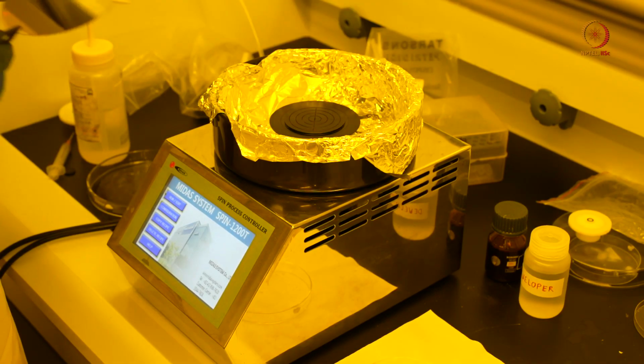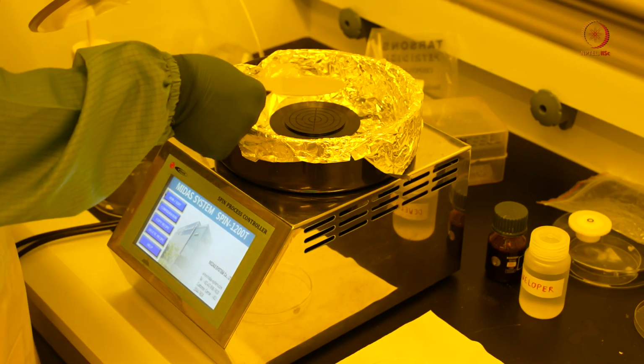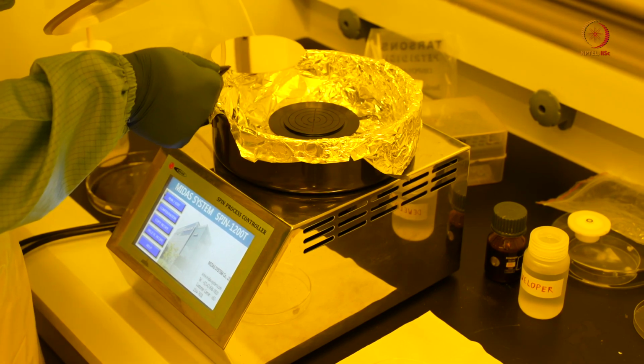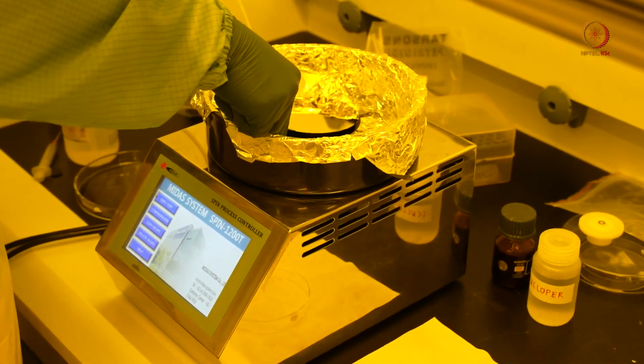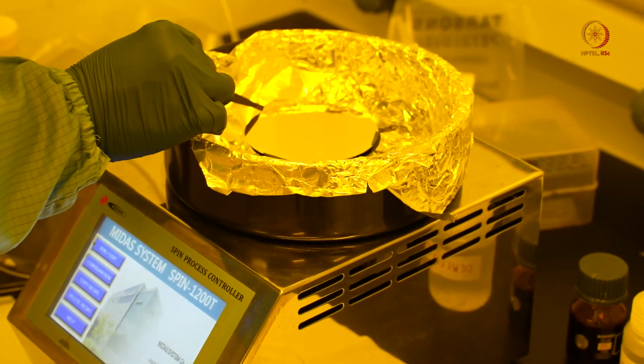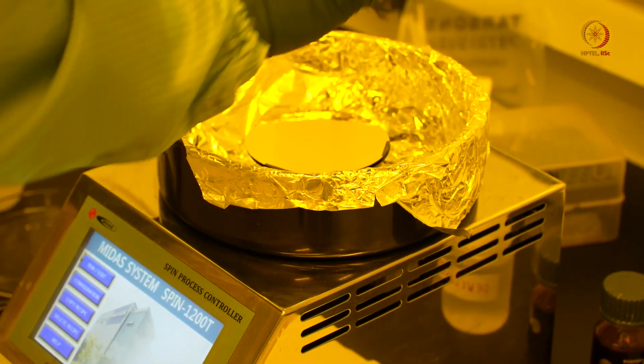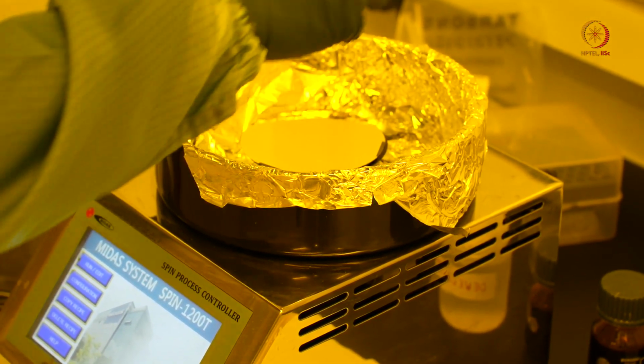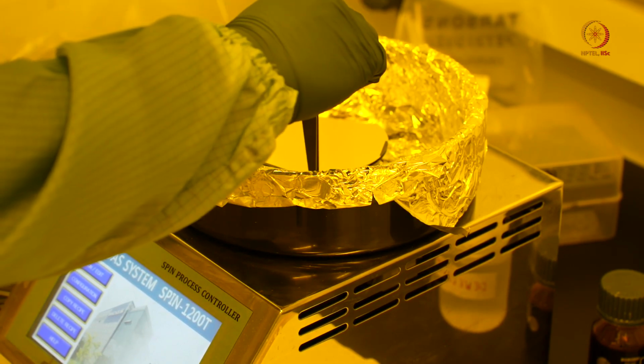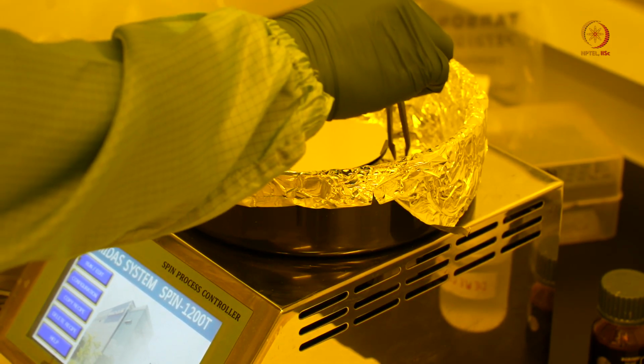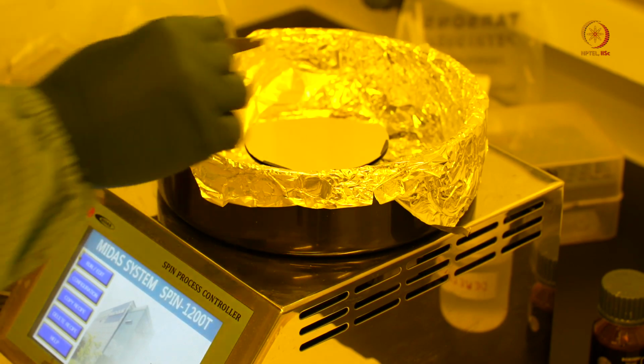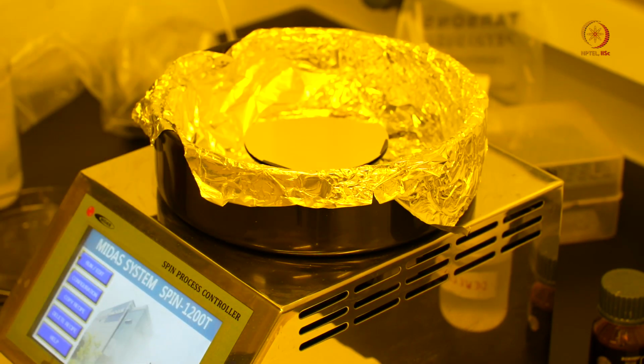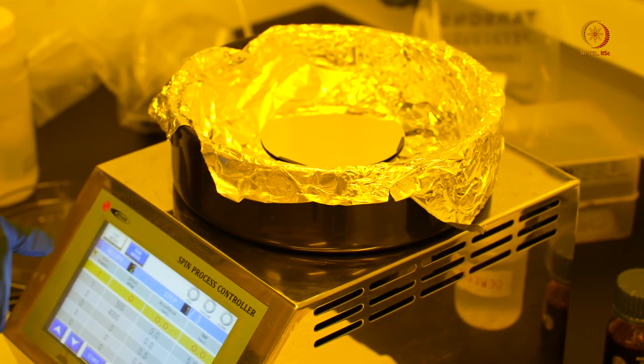So I'm opening the spin coater lid, placing the wafer on the chuck that we see here. So it's a vacuum chuck. Once we place the wafer and switch on the vacuum, the wafer will not be able to move, which is very important because we are rotating at around 4000 rpm, and if we don't hold it properly, the wafer will fly out. So then we select the recipe.